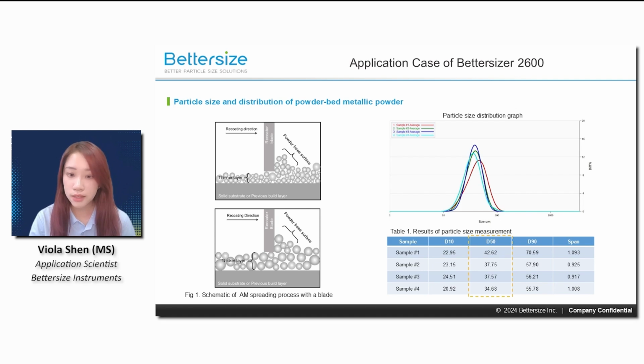Optimizing particle size and shape is crucial for improving the efficiency and quality of powder bed fusion. Therefore, in this case, the Bettersize 2600 was used to analyze these parameters of 4 powder bed metallic samples. The results are showing both the particle size distribution graph and the table 1 on the right.